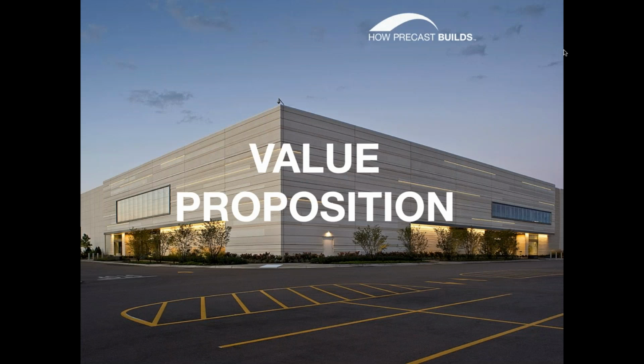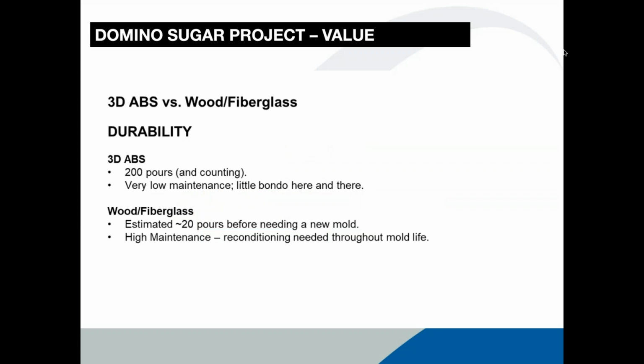So we'll talk about the value proposition and why you would use these versus a traditional form. What we did was compare a 3D printed ABS form to a traditional wood fiberglass, or wooden resined, form. We'll go through a variety of different value topics. The first one is durability. The last time we had contact with Gate, just a few weeks ago, they had poured on a couple of our molds 200 times, and they saw very little degradation in the form itself. I was told it's very low maintenance. They did a little Bondo here and there, not a big deal, but the molds have been holding up very well, even at the 200 pour mark.